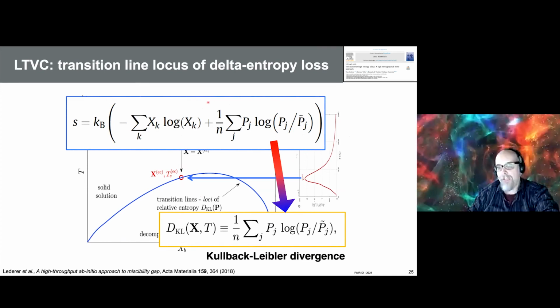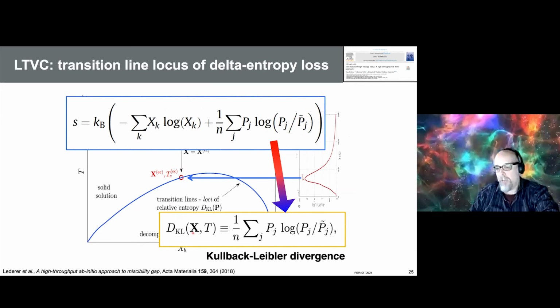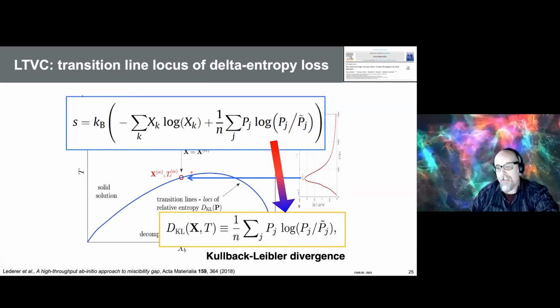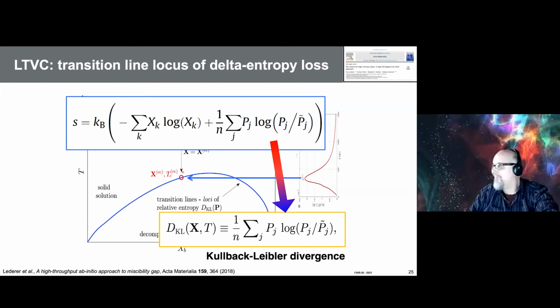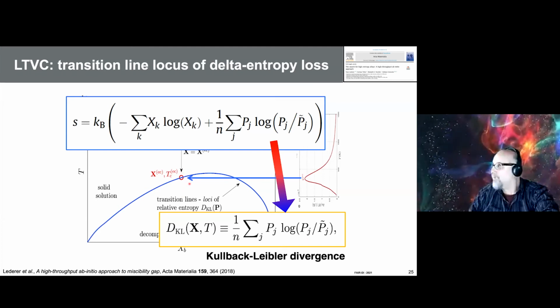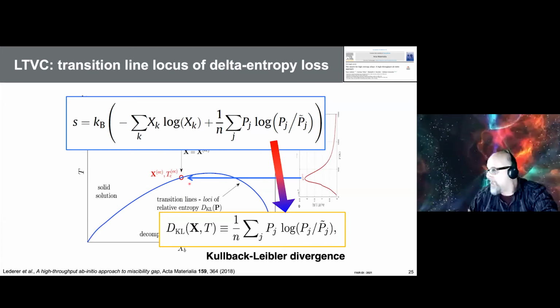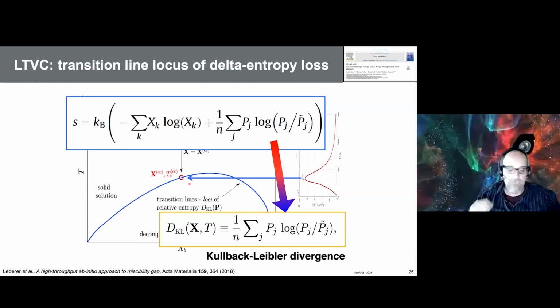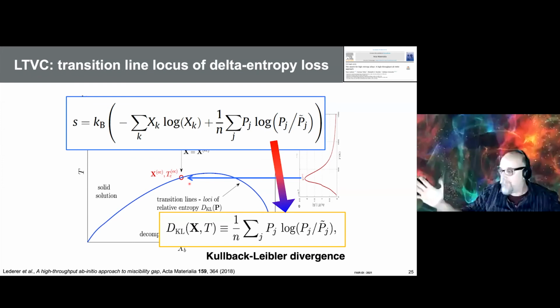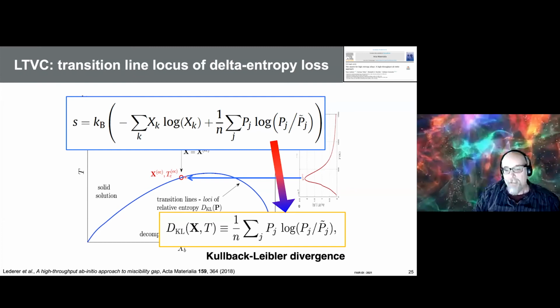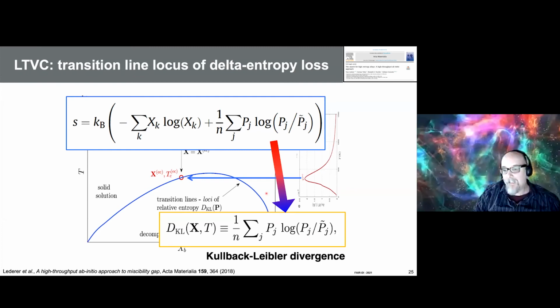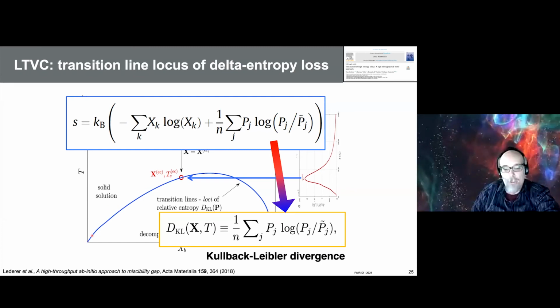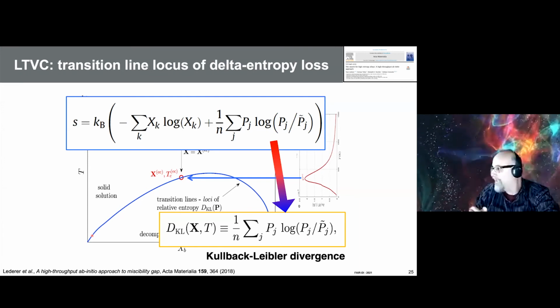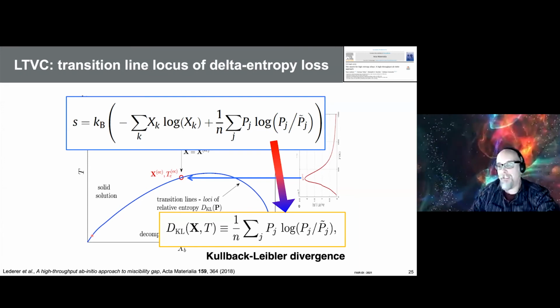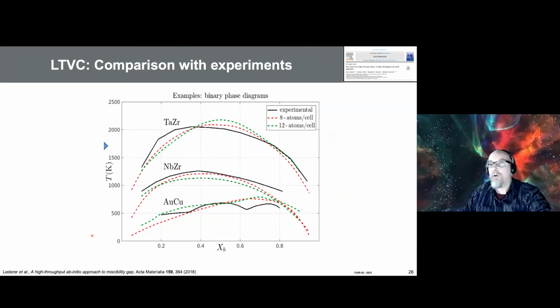This is going to be the second part of your S, which is called the Kullback-Leibler divergence. And then you say that the amount of relative entropy that you have lost, not the amount of absolute entropy, but the amount of relative entropy. You say, I lost 30%, I lost 50%, whatever it is, okay? The locus of the relative entropy loss being equal is going to be your miscibility gap. Guess what? It works amazing.